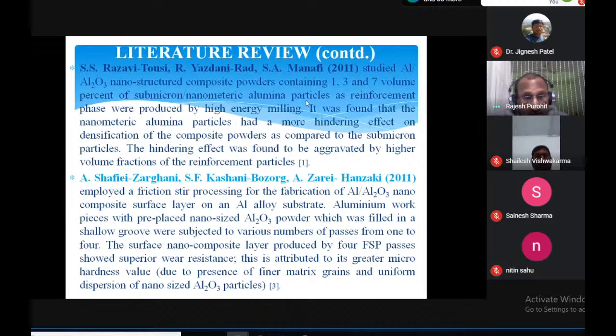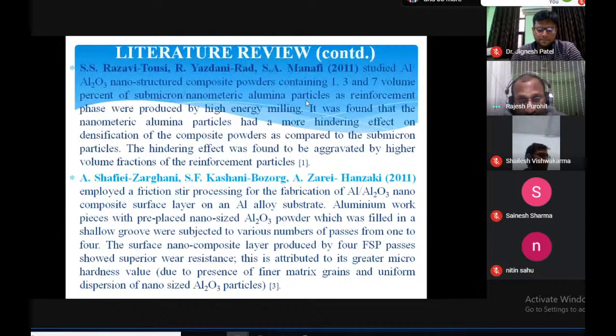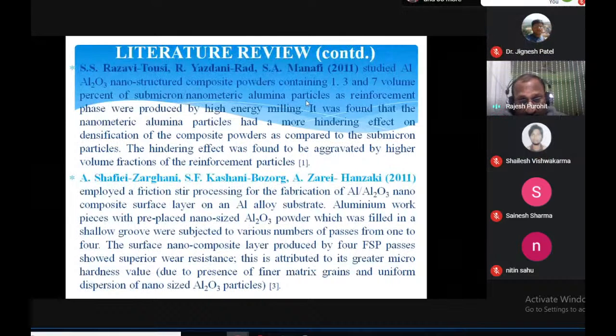Similarly, another author, A. Shafiei-Zarghani et al., have employed friction stir processing (FSP) for fabrication of an aluminum with nano alumina composite surface layer on the aluminum alloy substrate. As you must be knowing, by friction stir processing also we can make a surface composite. The work is with pre-placed nano-sized alumina particles on the surface, filled in a shallow groove. A groove was formed on the surface of the aluminum alloy substrate, in which the nanoparticles have been pre-placed.